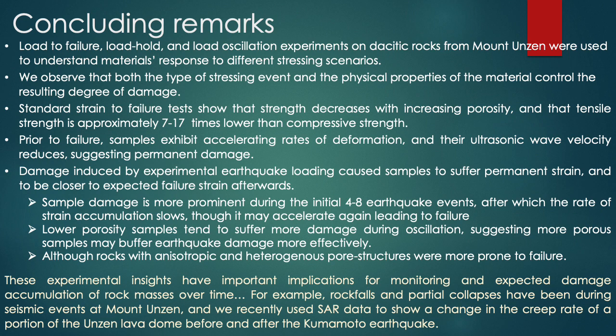We observed that both the type of stressing event and the physical properties of the material control the resulting degree of damage. Standard strain-to-failure tests show that strength decreases with increasing porosity and that compressive strength is 7 to 17 times higher than tensile strength. Prior to failure, samples exhibit accelerating rates of deformation and their ultrasonic wave velocity reduces, suggesting the onset of permanent damage.